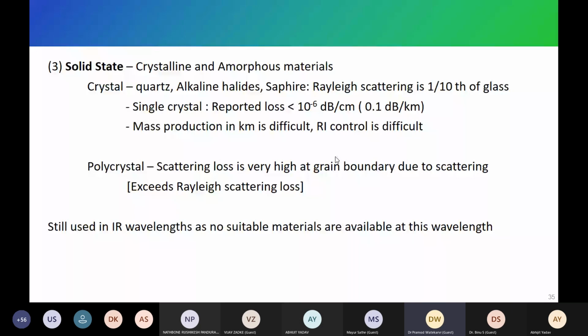So crystals are very good, but it's very difficult to mass produce. We need kilometers of fiber, right? We have to go from India to America, European countries. We need to communicate on that scale. We cannot manufacture a crystal at that scale. It's very difficult. The second thing is we cannot draw fiber with crystals. So crystals are not used in optical fiber communication. We don't make it. And then people said, okay, if crystals are so difficult and take a long time to manufacture, we can use polycrystals, right? Polycrystalline structure. But soon this idea was dropped because it showed huge attenuation. Huge absorption was there because of scattering. If you send some power, the output power was very low. So crystals, don't use, gone.